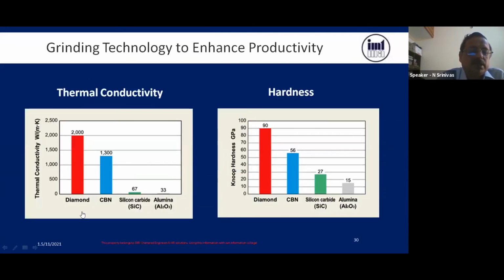And this is the thermal conductivity of different types. For example, diamond thermal conductivity is around 2000, CBN is 1300, silicon carbide 67, aluminum oxide 33. This is very soft and this is very hard. Diamond is the hardest. If you take hardness, diamond is 90, and its heat resistance capacity is also highest at 2000, whereas CBN is 56, silicon carbide 27, and aluminum oxide 15. This is only a comparison.